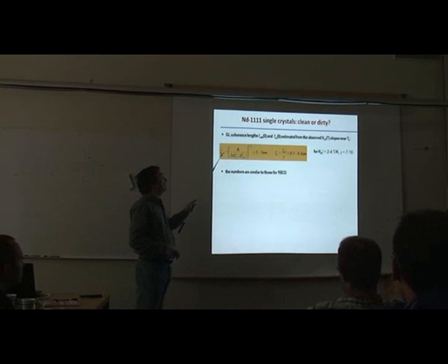So, what can we extract from these measurements? Well, from this measurement we can extract the coherence length, which tells us about the size of the Cooper pair. Simply, the Ginzburg-Landau theory tells us that if we know the slope of Hc2 near Tc, we can calculate the coherence length. This is the flux quantum, that is Tc. For the numbers we have, we get something around 20 angstrom. 20 angstrom, that's what we have in cuprates. So the size of the Cooper pair in these materials is small.